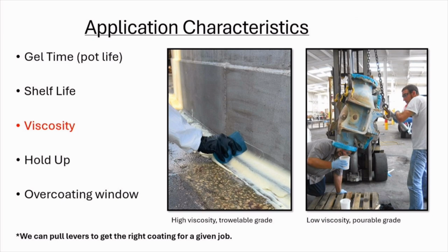Viscosity, so I have a couple pictures here to illustrate viscosity. One of the levers that we can pull whenever we're making coatings to make them effective for the given use is viscosity. So the same chemistry and the same service, the same resistance, but in 2 different thicknesses. So in certain cases, like whenever you're looking at a cove base or when you're trying to fill pits, you want something that's thick and can be trowel applied. In this case, they're using a little Bondo knife.